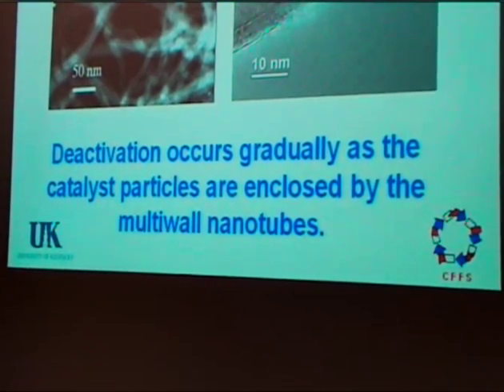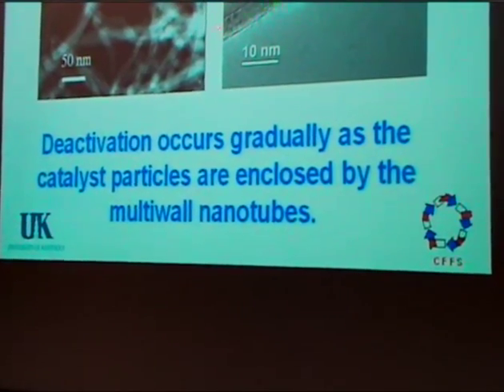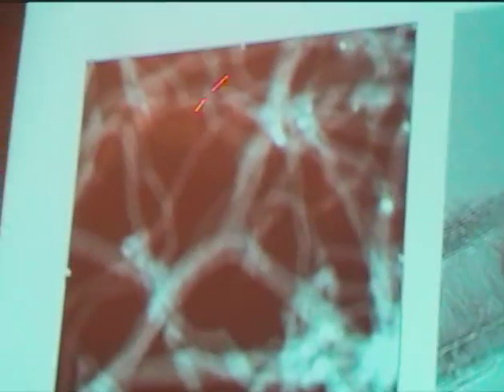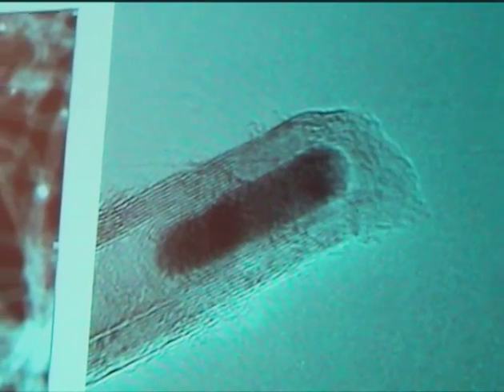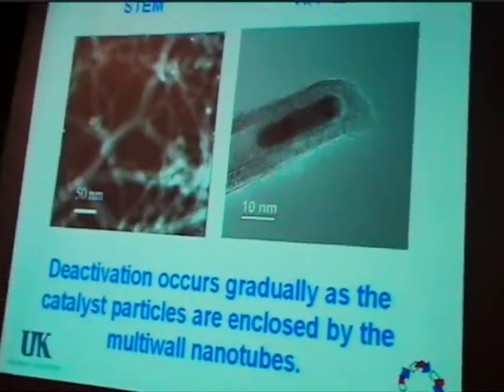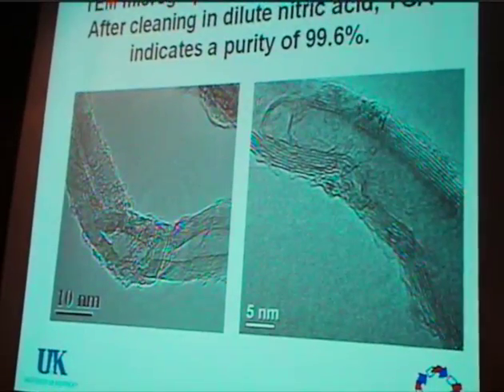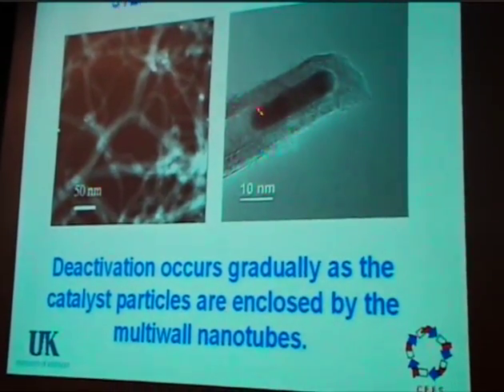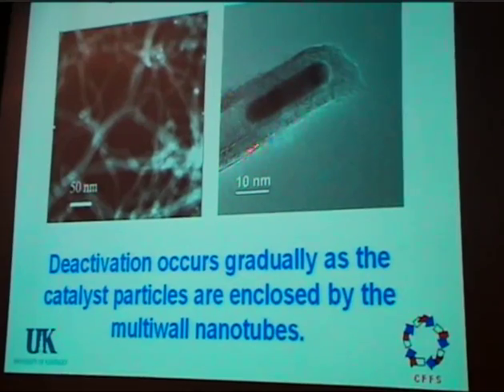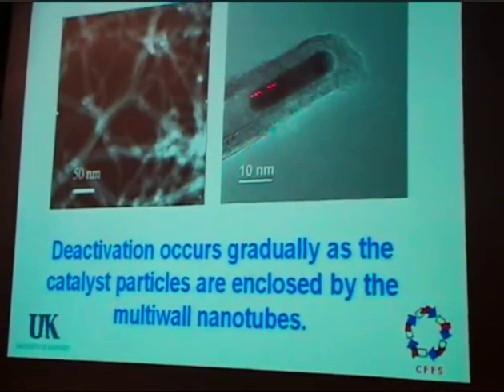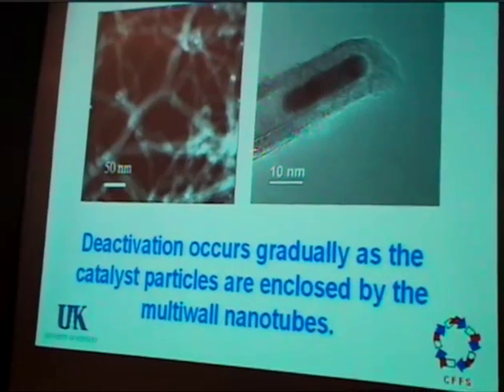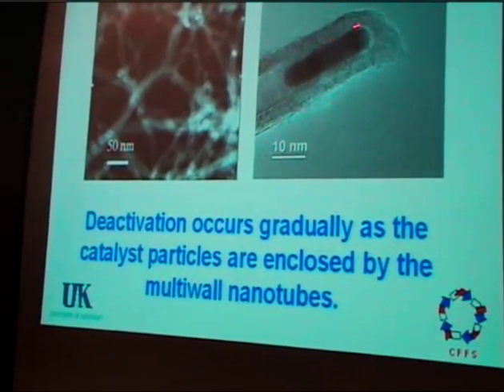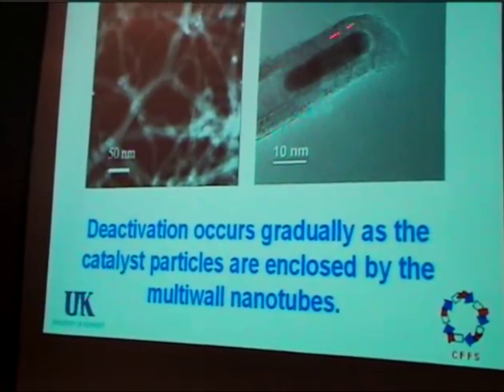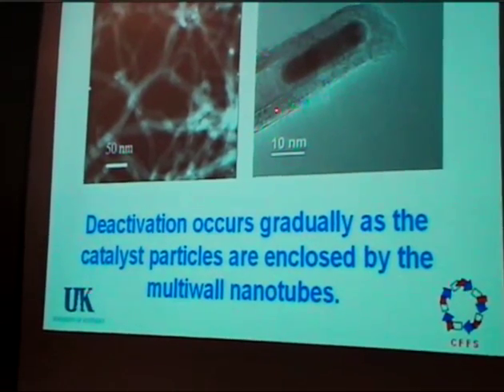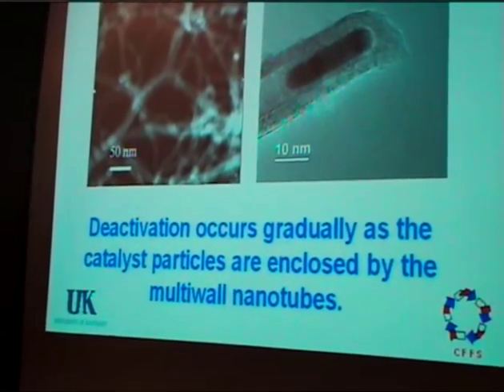It appears to occur primarily because the catalyst particles are doing tip growth here, and they're getting embedded inside of the nanotubes, and when they get surrounded, gas no longer gets to them, and that apparently is the deactivation mechanism. You can see a catalyst particle encapsulated in a tip up here. It's elongated. I'm not exactly sure why that happens, but I'm sure there's a good explanation for it. Maybe some nanoparticle nanotube person here can tell me about it. But that's the deactivation mechanism.